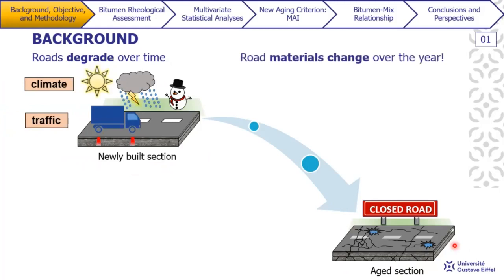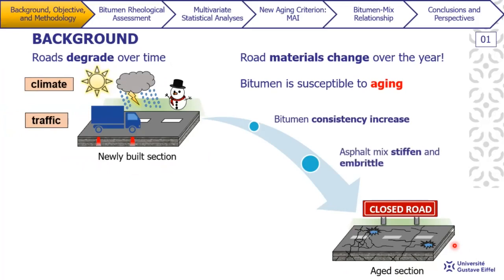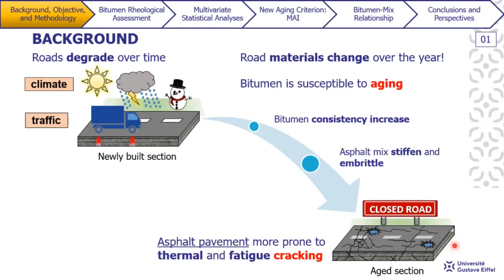Well, in addition to climate and traffic, the degradation of our roads can mainly be due to the changes experienced by the material often used in road constructions, like bitumen, for example. Because of its organic nature, bitumen is susceptible to aging. Well, in this case, the irreversible changes triggered by aging will lead to an increase in bitumen consistency over the years, which will cause asphalt mix to stiffen and embrittle. And consequently, we're going to end up having our asphalt pavement that is now more prone to thermal and fatigue cracking.